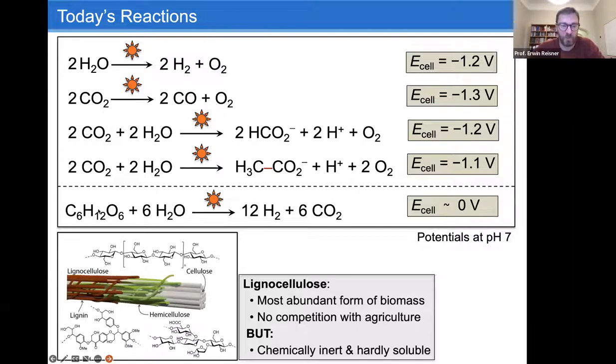The one type of reaction that's a bit distinct is the one when it comes to waste reforming or waste oxidation coupled to fuel synthesis. So I just show one reaction here. This is glucose. And I'm showing glucose just as a model substrate from cellulose that I will show in a second. And if you convert glucose with water into hydrogen and CO2, you will see that this Gibbs free energy is roughly zero. So we are thermoneutral, and the solar energy really just provides the energy input to drive the kinetics, so overcome the kinetic barriers to drive the reaction. So in all systems where we are using waste, a single light absorber is sufficient, which is a significant advantage in terms of rate of catalysis.